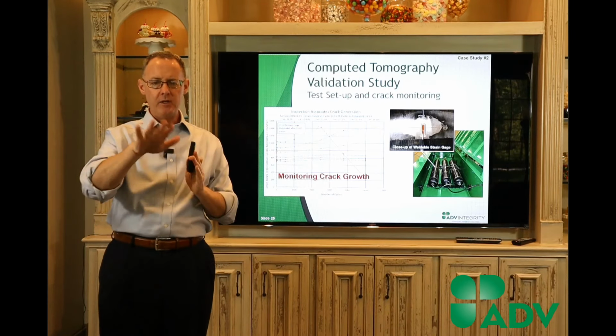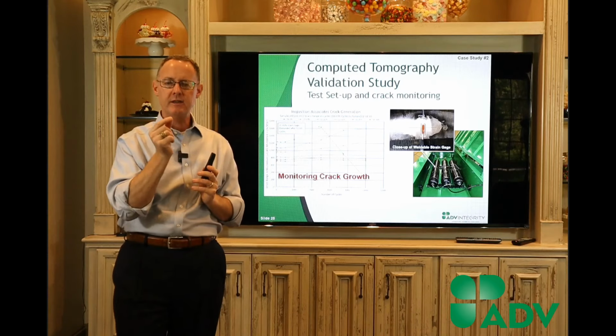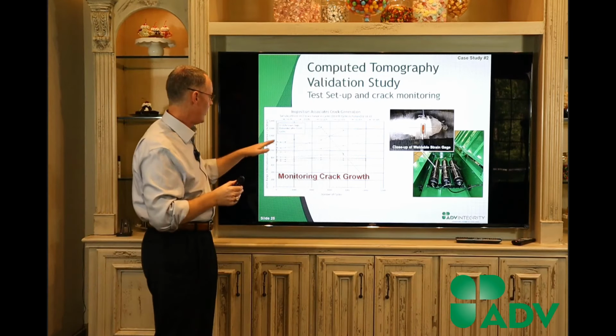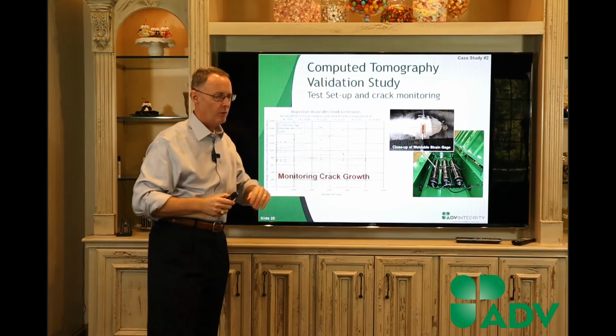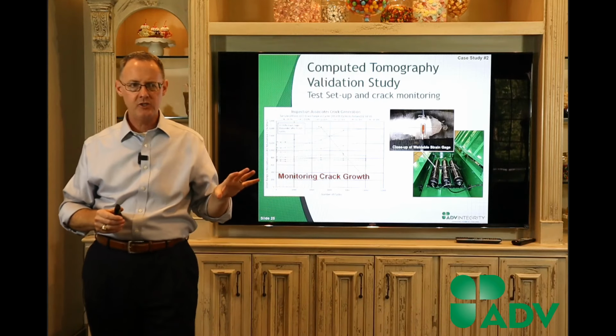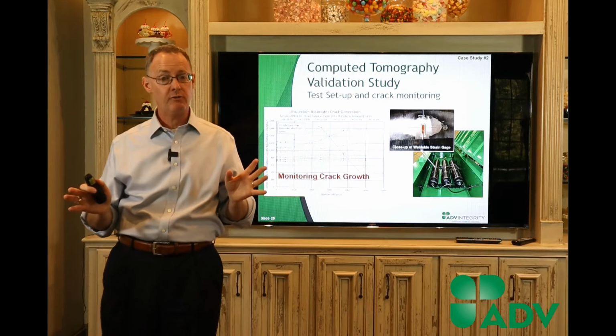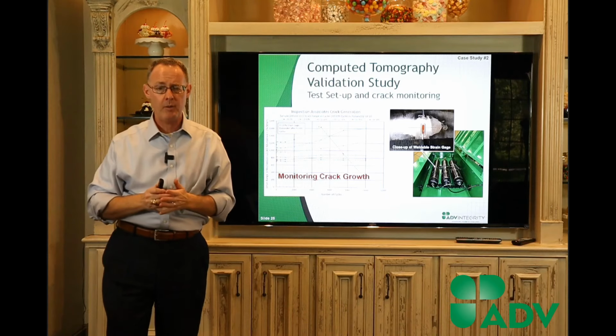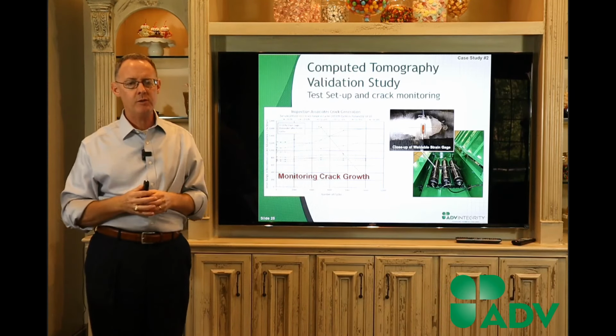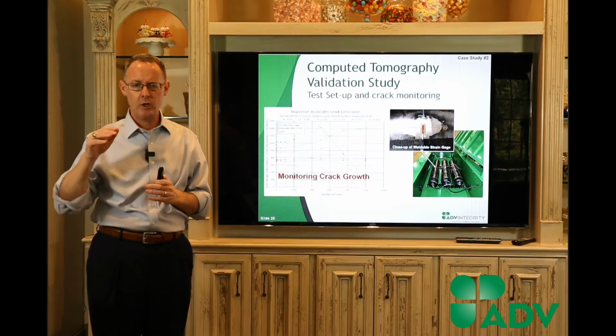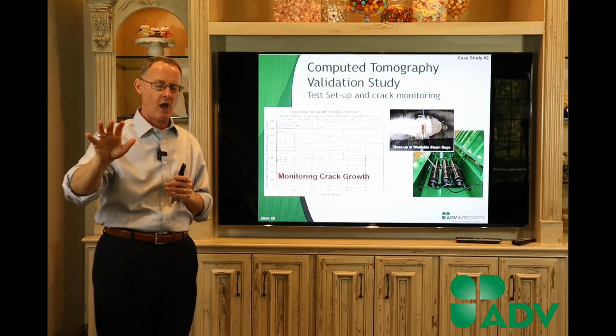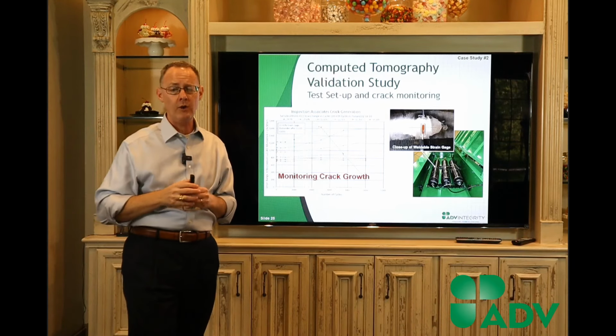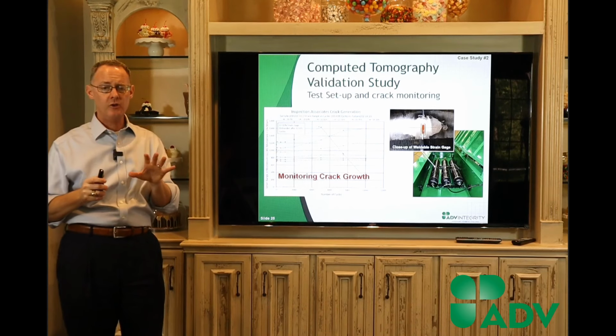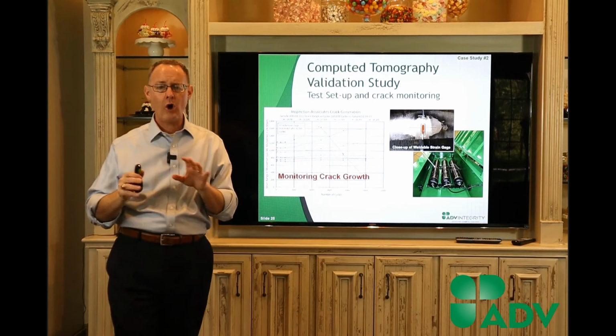And as it opens up, what you see is the compliance in that notch changes and the strain really starts going up. And so we did a project with James Medford working on this. We did a big project for Rosen that we also presented a paper at PPIM. So, we developed some expertise on this in terms of really determining when do you stop. We've got some other things that we're working on as well to really kind of help us understand where are we in terms of how far the crack's propagating.